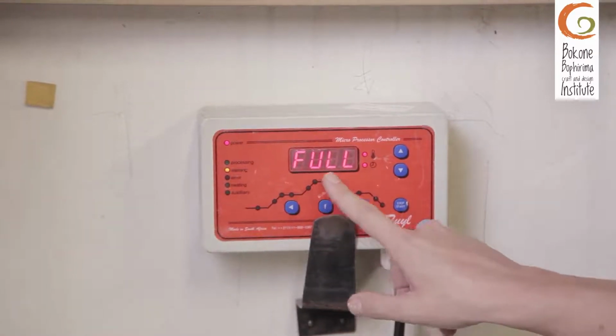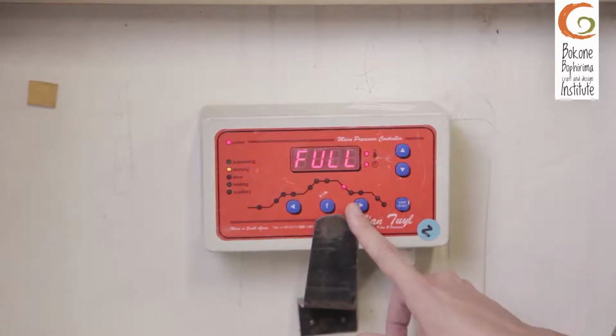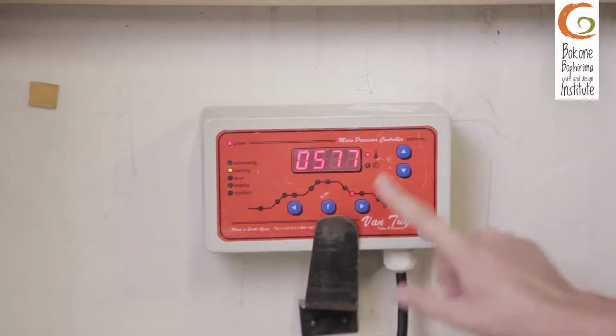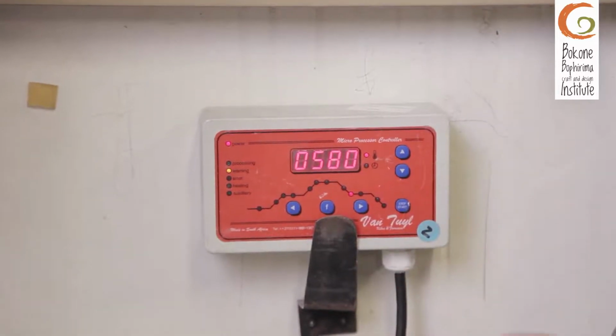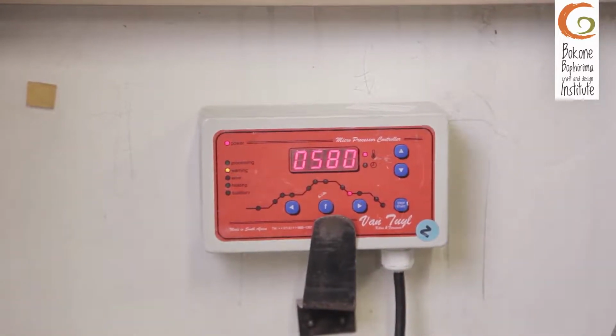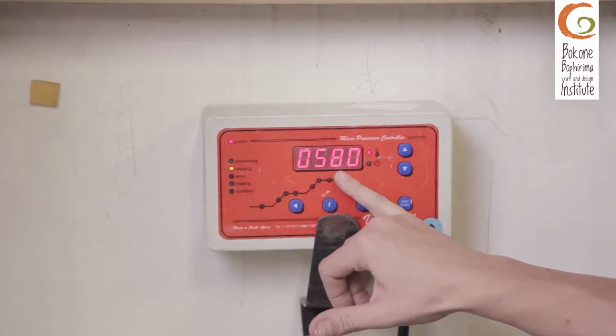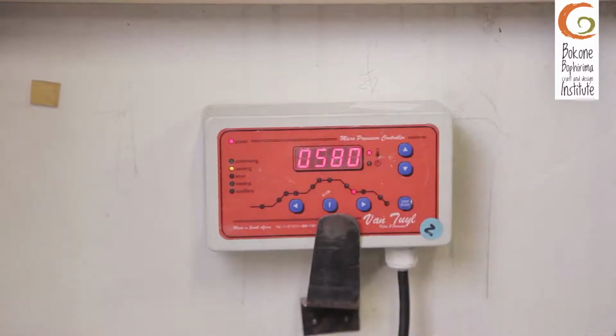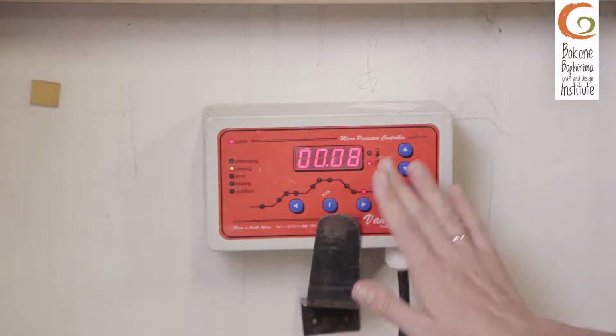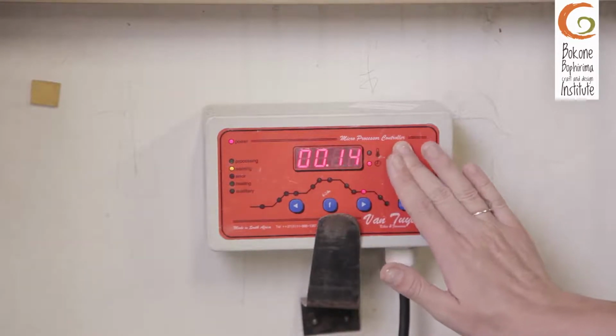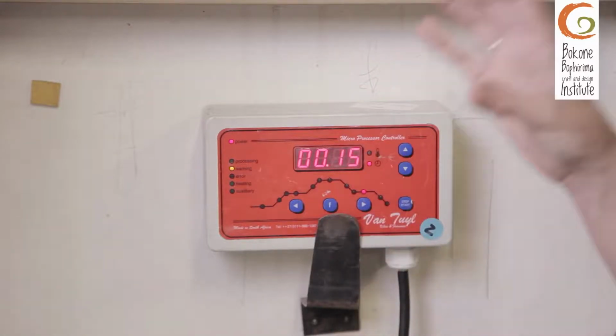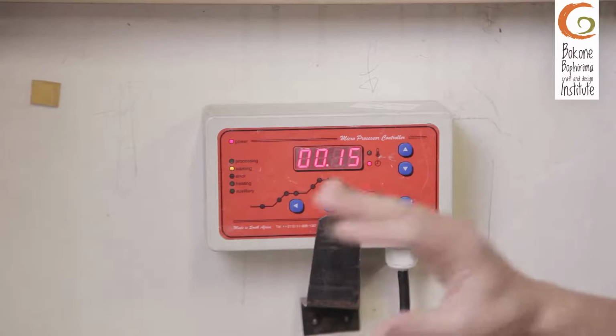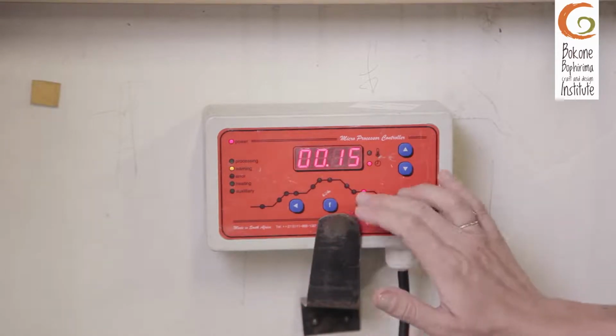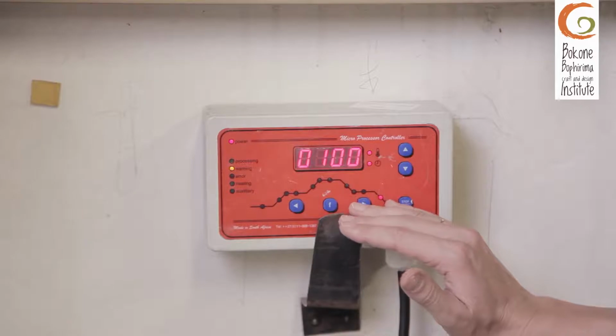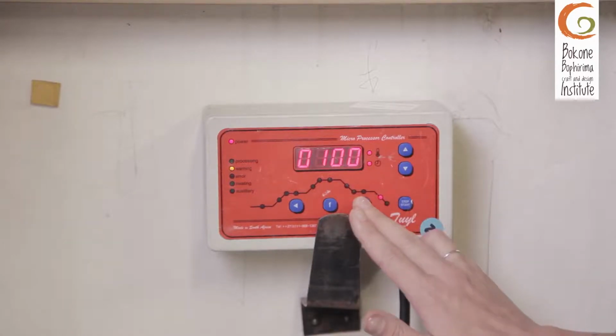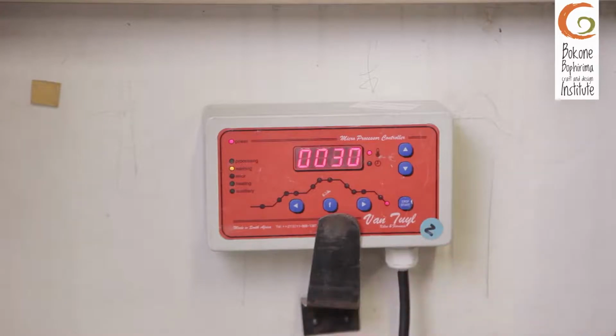I'm then going to bring it down as fast as possible because I'm doing this via the kiln crash cooling, and I'm going to take it down to 580, and this is again where our glass becomes fragile. So from this temperature, from 580, we are bringing the glass down slowly again. Well, first I'm going to hold it for 15 minutes to ensure that the entire piece of glass that we fused is all 580. And then from that, I am going to bring it down 100 degrees an hour, and this process is called annealing, until 30 degrees or room temperature where we can open the kiln.